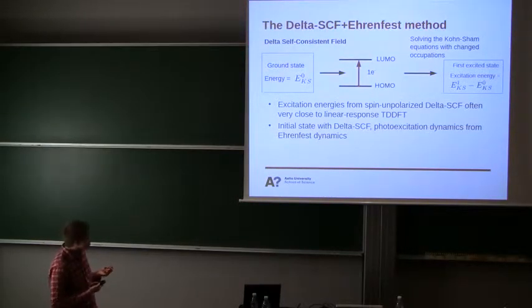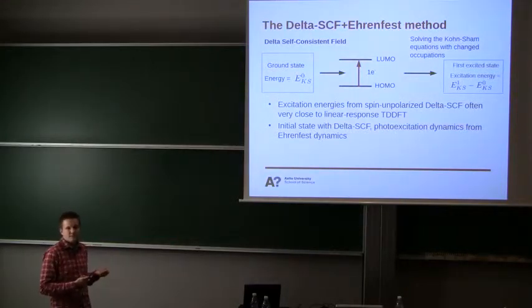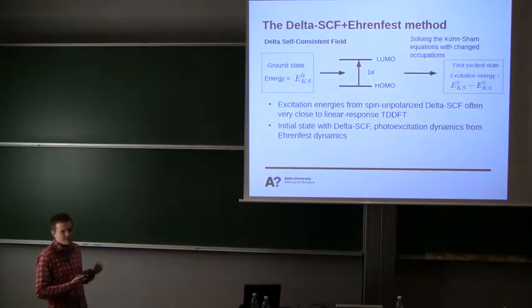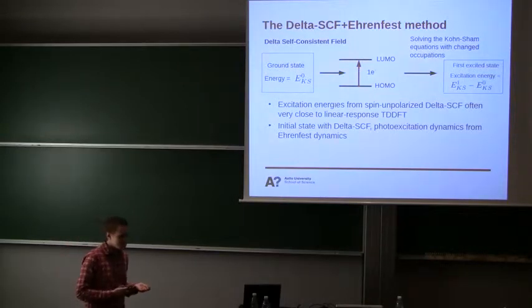And it actually turns out that for certain systems, and in the case of gold clusters, the fortunate case is that the spin-unpolarized version of delta SCF gives energies that are pretty much similar to linear response TDDFT, which is typically used for studying gold clusters. So to calculate the photo-induced dynamics, we create the initial state using delta SCF and then run Ehrenfest dynamics from there.